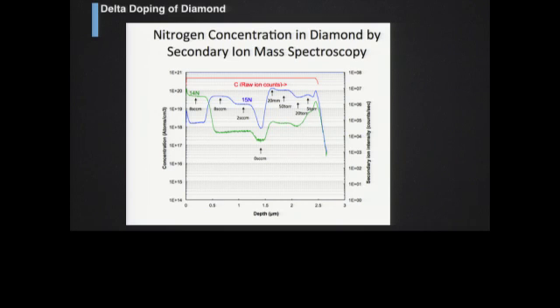And when you buy nitrogen 15, it is not as pure as you might think it is. It has about 5 to 10% of nitrogen 14 in it. But we wanted to make sure that it was tracking according to our gas concentrations, and we were looking at nitrogen as opposed to looking at silicon. And we wanted to make sure there was no out diffusion from the substrate in the case of silicon carbide or silicon.